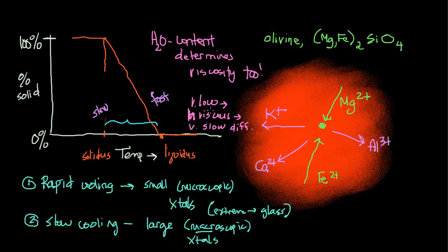And the reason we see glass is because these compositions are particularly very, very poor in water. And under those conditions with very little dissolved water, the diffusion rates are so slow that even with a couple weeks of time, there's not enough time even to grow a little seed crystal, and we end up with glass. So don't always assume that if you see glass it must mean that the cooling rate was extremely fast, because it can also occur with very, very dry liquids.